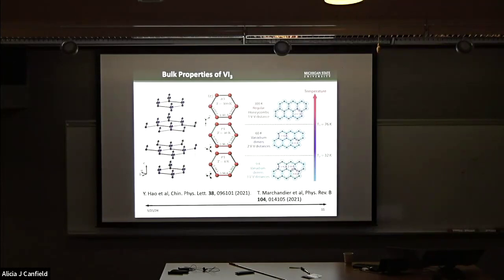And recent single crystal neutron diffraction measurements done by the Oak Ridge group and a group at Fudan University found that actually the easy axis of vanadium triiodide is slightly tilted away from the C direction. And both the neutron diffraction as well as the synchrotron X-ray diffraction found that below the structural phase transition, the honeycomb lattice of the vanadium ions is slightly distorted.